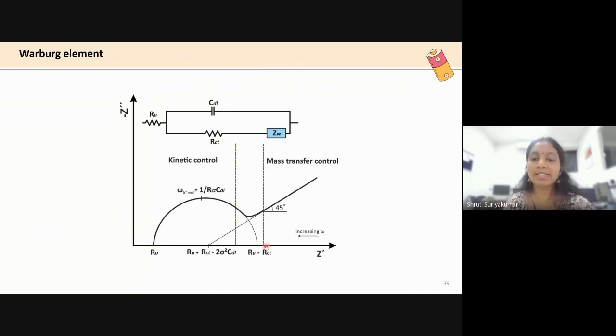Say for example, my Ru plus RCT is coming around 40 to 50 ohms, and yours is turning out to be close to 20 or 10 ohms. Again, we will be able to say that you have prepared your electrodes better, your coating is better, and therefore your cell is obviously going to perform better. So even before running our cells, if you have a cell and I have a cell, if we plot a Nyquist plot and look at the expressions and the values, we would be able to correlate it with how good your experimental results are going to be. So that is the basic idea of the entire fitting and analysis parameters.